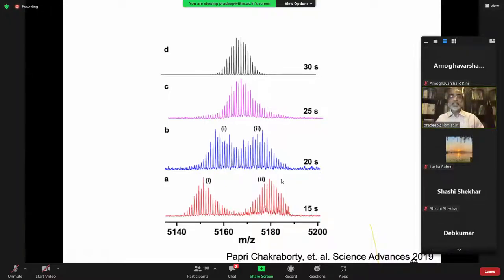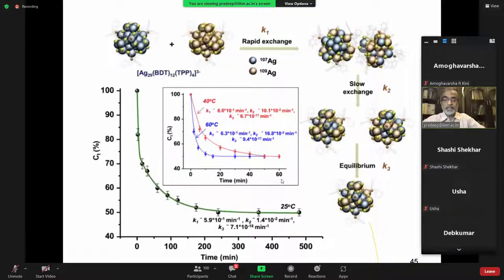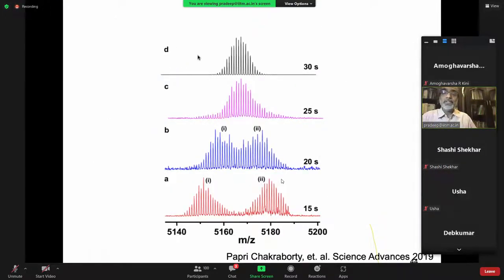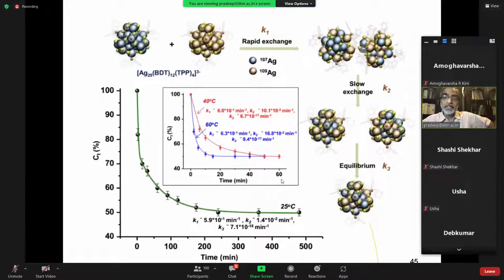Such a fast, extremely interesting atom exchange tells you that they are indeed molecular systems. Can you study the dynamics, the rate of this exchange? Mass spec took quite some time in this particular case, because the time taken is only 30 seconds. We don't have enough mass spectral data to get good rate constants. But here we did this experiment with Ag25. And this exchange could be studied over a long time, and it took quite some time to equilibrate. But we saw that the initial exchange is quite fast.